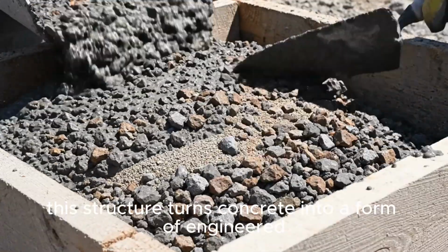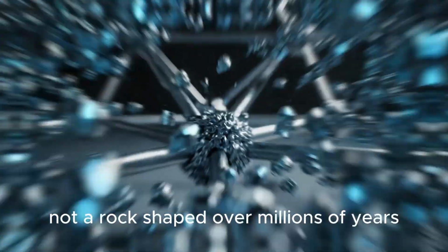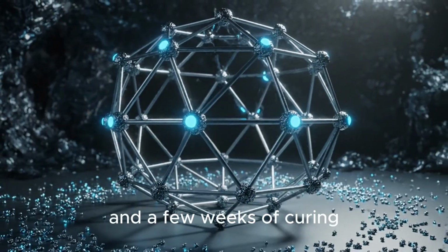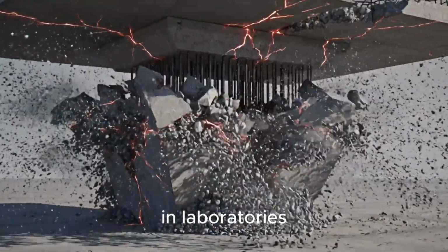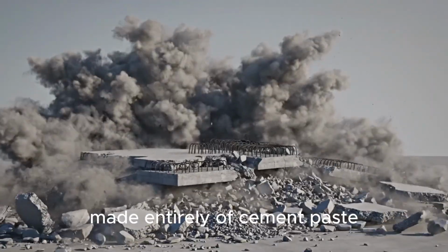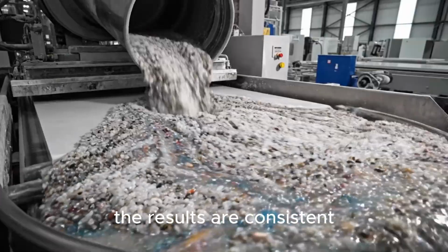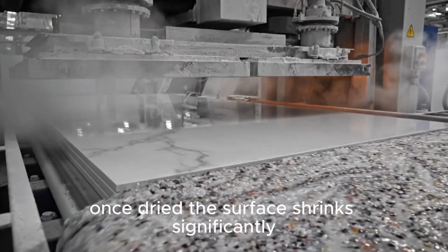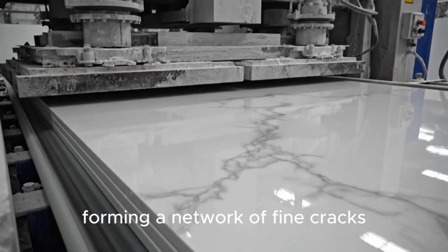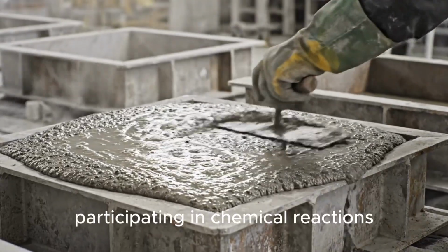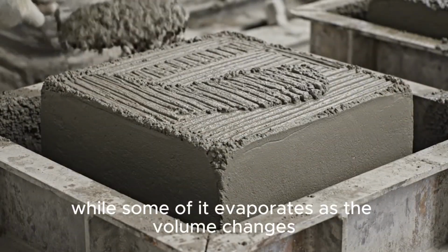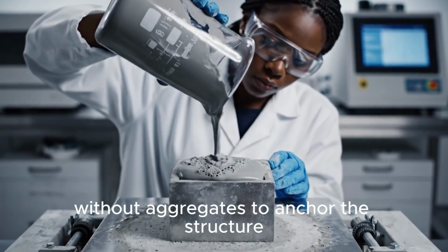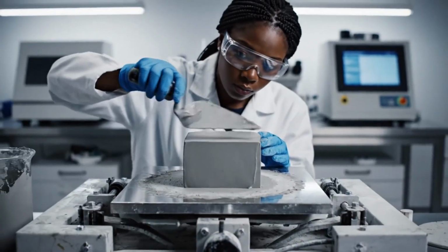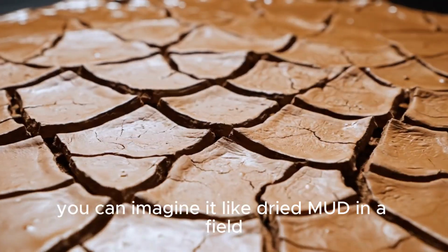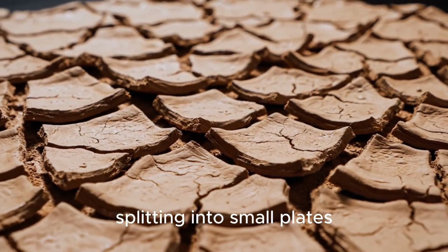This structure turns concrete into a form of engineered stone, not a rock shaped over millions of years, but one designed in a few hours of mixing and a few weeks of curing. In laboratories, researchers have cast samples made entirely of cement paste. The results are consistent. Once dried, the surface shrinks significantly, forming a network of fine cracks. This shrinkage comes from water participating in chemical reactions, while some of it evaporates. As the volume changes without aggregates to anchor the structure, internal stresses appear. You can imagine it like dried mud in a field, splitting into small plates.